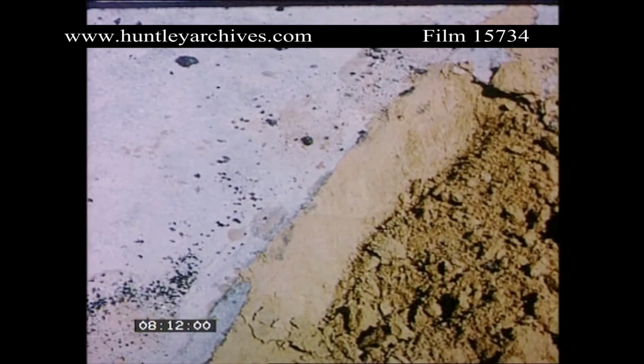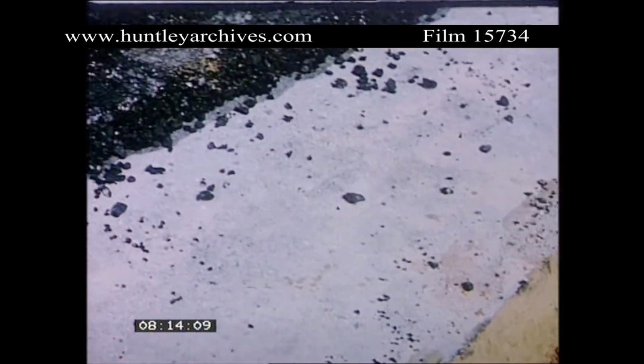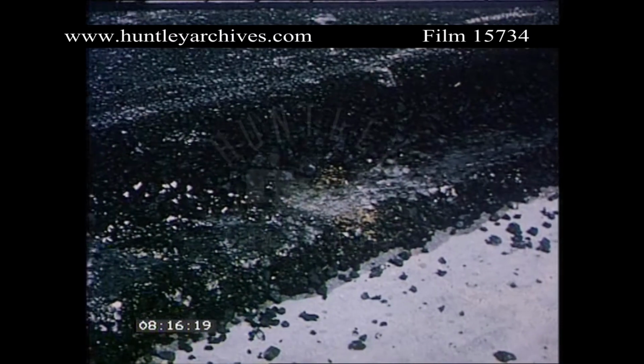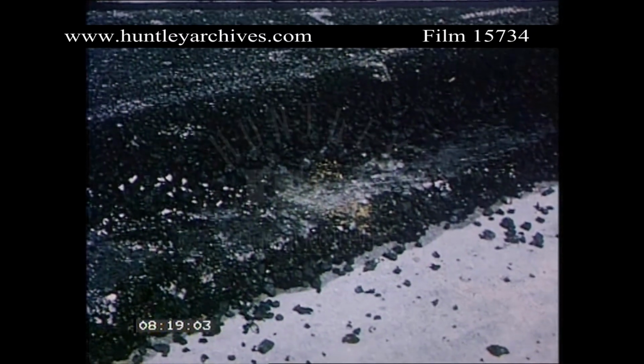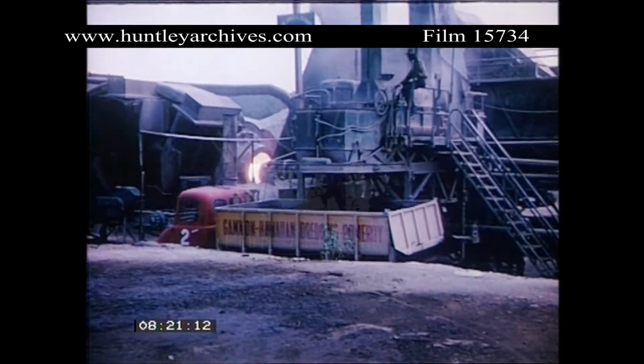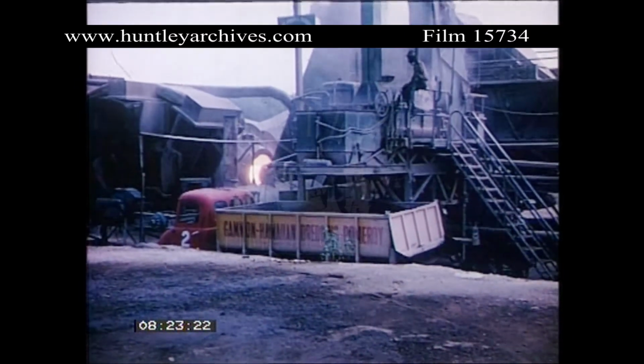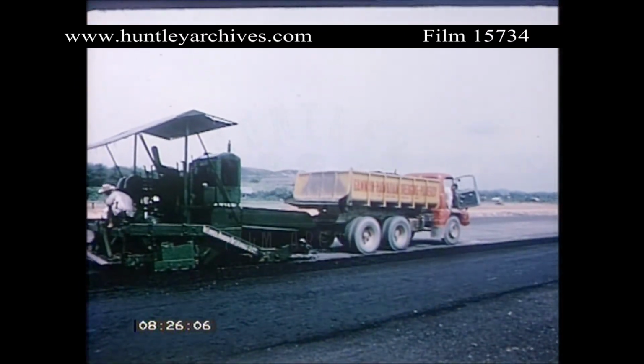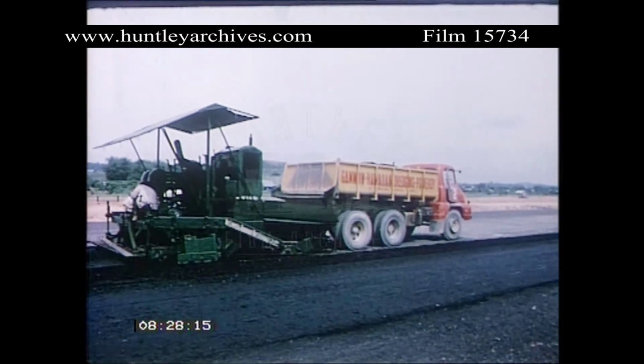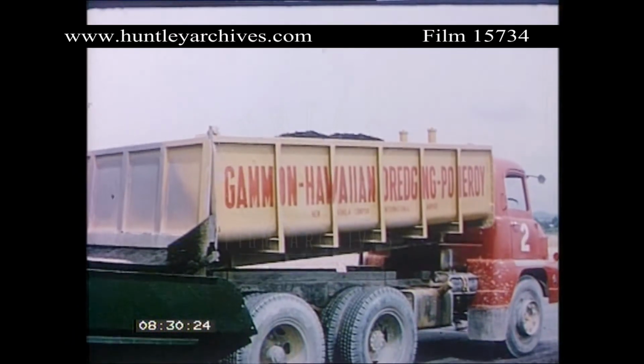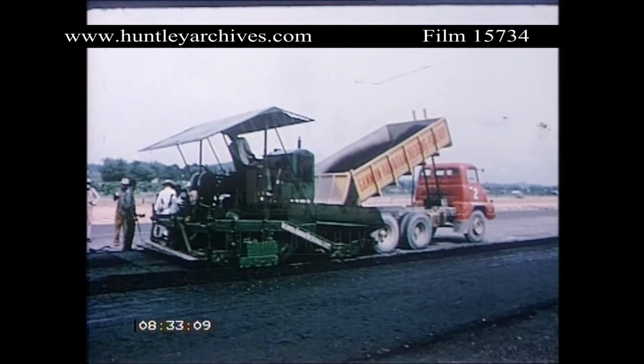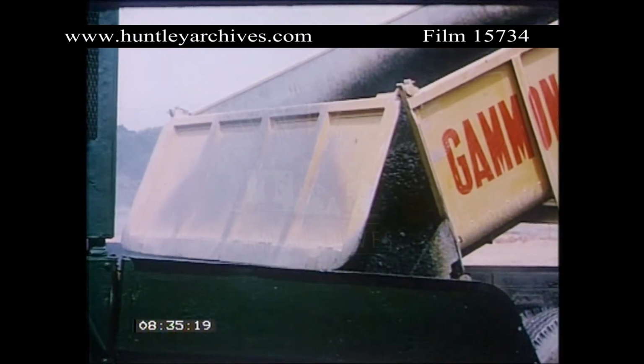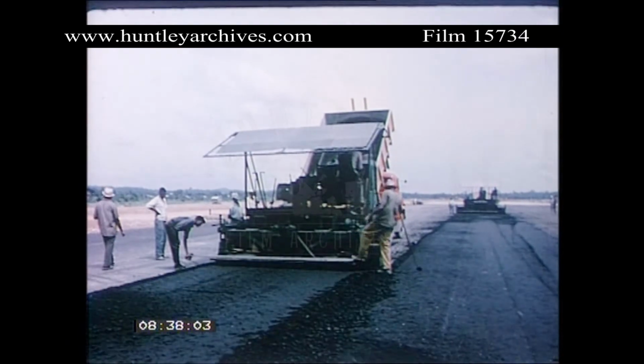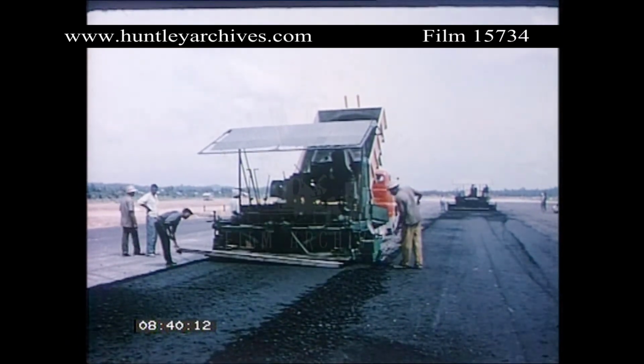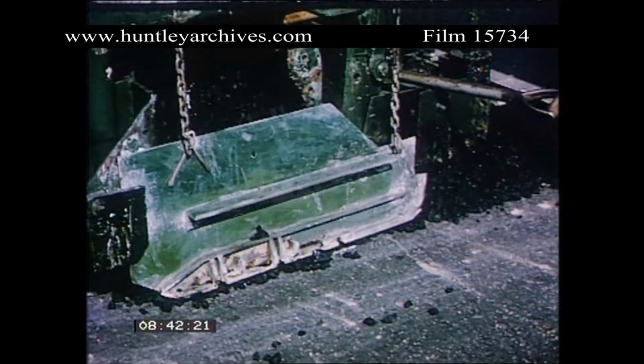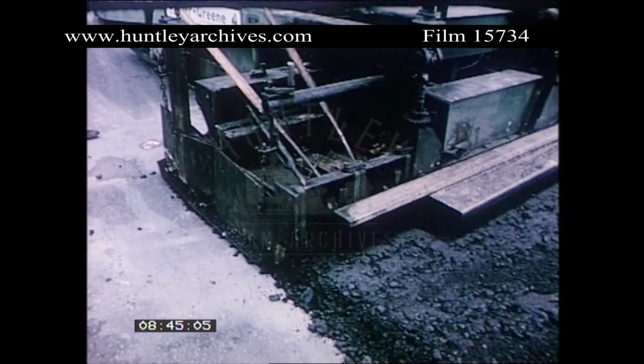After the stabilized soil had cured for 7 days under a prime coat of cut-back bitumen, the bitumen-bound base was constructed. The material was mixed using a Barber Greene mixing plant. The aggregate was made up with 40% crushed granite of 1.5-inch nominal size, with sand waste from local tin mines and 2% filler. A bitumen content of 3.3% was added to give a Marshall stability of at least 650 pounds. A Barber Greene spreader was used to deposit the 3 4-inch thick layers of the base material.